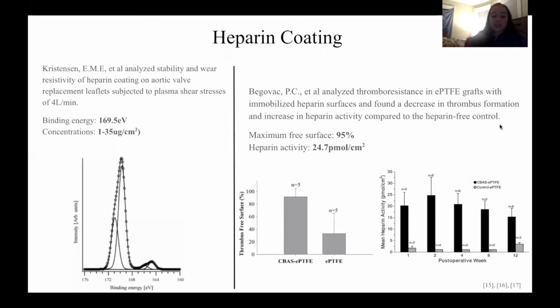Two other studies were used to evaluate the effectiveness of incorporating heparin onto our device. The study on the left characterized the binding surface energy of a covalently immobilized heparin coating on a replacement aortic heart valve, which was found to be 169.5 electron volts. The study on the right compared thromboresistance in ePTFE grafts with the covalently bonded heparin coating. The coated graft resulted in a 95% thrombus-free surface and a heparin coating activity of 24.7 picomoles per square centimeter, which are two target values our device would aim to exceed in order to maximize antithrombin binding to reduce